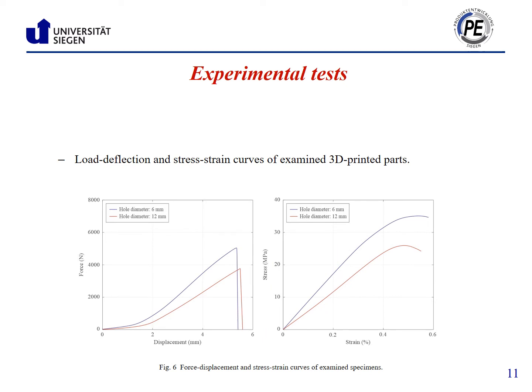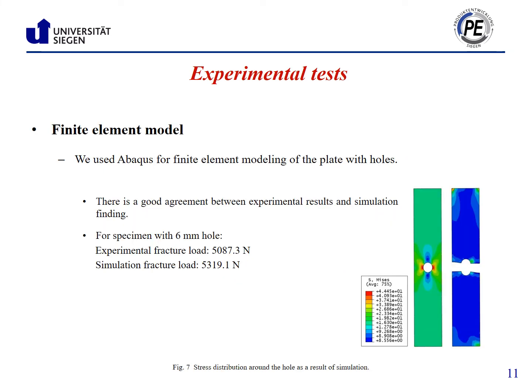In this slide, load deflection and stress strain curves of the examined specimens are illustrated. As you can see in the left figure, fracture load decreased with an increase in the hole diameter. Also, the figure on the right side indicated that the slope of the stress strain curve of the specimen changed with a change in the hole diameter. In this study, we used Abaqus for finite element simulation of the plates with hole under the tensile load. Here you can see a stress distribution around the hole as a result of simulation. There is a good agreement between experimental results and simulation findings.